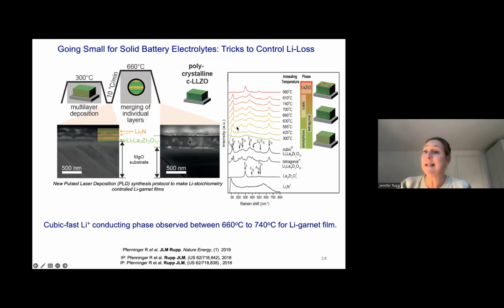And this is what we can see in the Raman spectra. Raman spectra are great. They look at the molecular vibration that you excite. And it tells you, for instance, a lot also about the lithium-oxygen bond. So that's why we like it to study phase evolution. And if you look at around 650 degrees Celsius, we get towards a reference, which is the cubic fast conducting phase in the lithium garnet, the exact same phase, but now in a thin film.